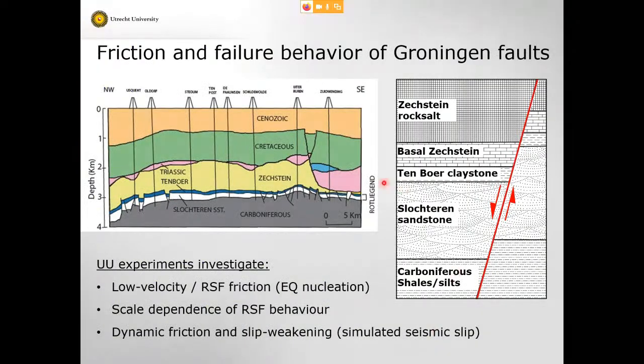So what we did basically, here's an enlargement of the stratigraphy around the reservoir. Here's the sandstone. Here's a typical fault offsetting the reservoir by something in the range of 20 to 50% of its thickness. That's typically what you see. And below there are these Carboniferous source rocks, shales and siltstones, and this very clay-rich Ten Boer claystone rock here. And this is an anhydrite carbonate evaporite at the base of this evaporite sequence.